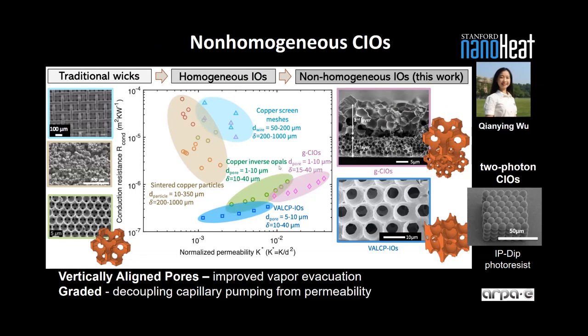This is one route, and it basically gives you your cake and allows you to eat it too, because a traditional copper screen or sintered copper particles, this is old school heat transfer, have a large thermal resistance and they give you a low permeability, but the penalty is a large temperature rise. And with some of these structures, vertically aligned inverse opals, we can achieve simultaneously a low resistance and a reasonably high permeability.